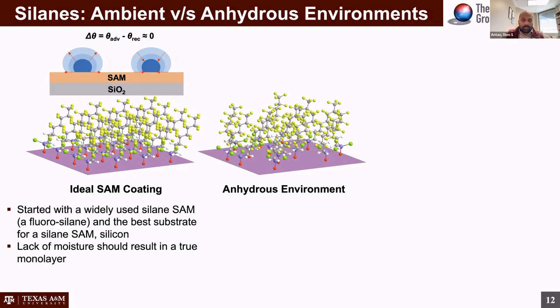But in our real world, the best we can do is an anhydrous environment, so no water vapor, no water, no dissolved water in the solution, etc. And because of the presence of gauche defects on the tails of the silanes, you can have misorientation of the molecules. They're not all in the same direction. Depending on temperature, the molecules are vibrating around at the molecular scale. And so again, it's possible that you're not always orienting in the right direction. And so you can have some level of defects on the surface. And at the moment, that's the best we can hope for, but we've not really explored this area enough at the molecular scale from a modeling perspective, which is some of the next steps of what we're doing.